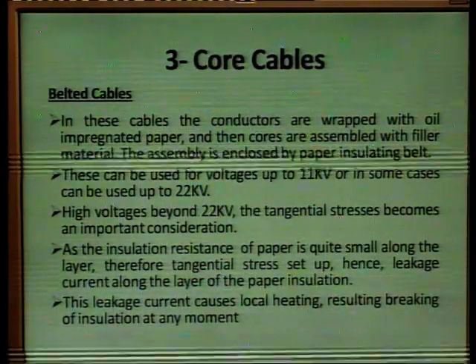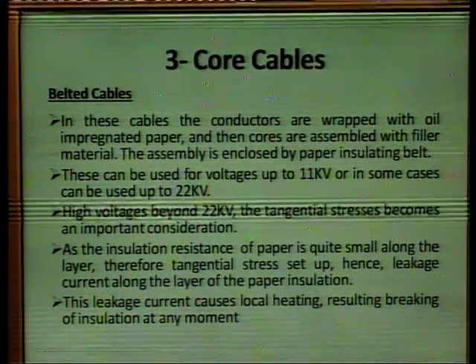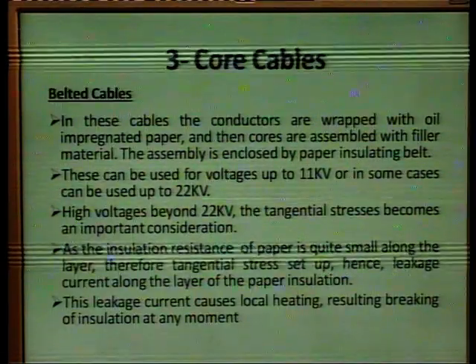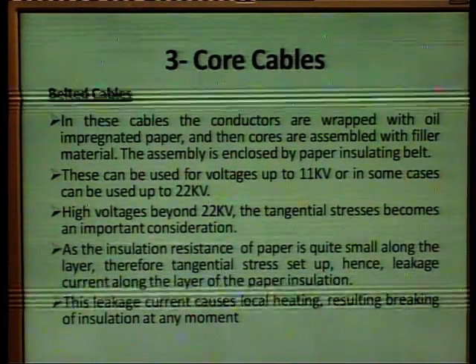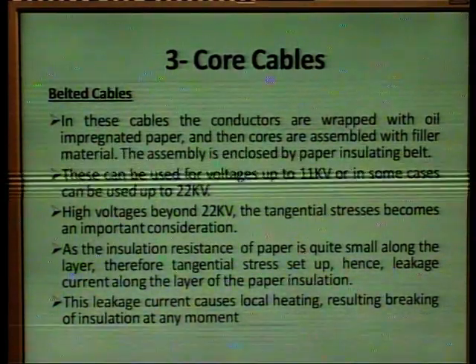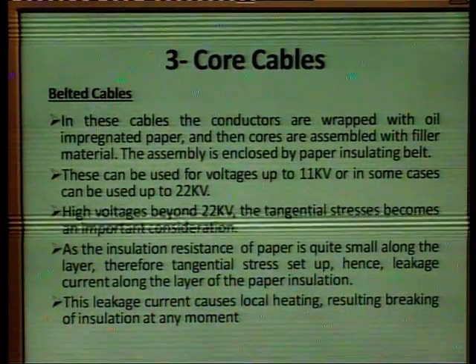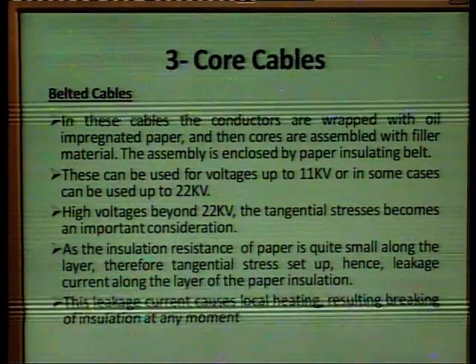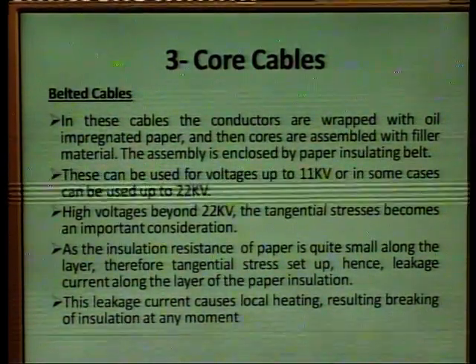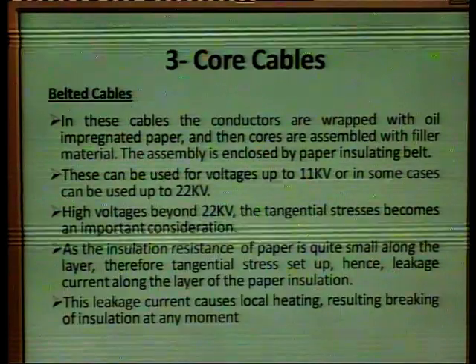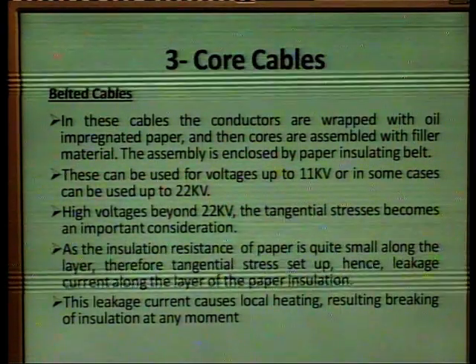Then for high voltages beyond 22 kV, the tangential stresses become an important consideration, as the insulation resistance of the paper is small along the layer. Therefore the tangential stresses set up a leakage current along the layer of the paper insulation, and this leakage current causes local heating, resulting in breaking of the insulation at any moment.